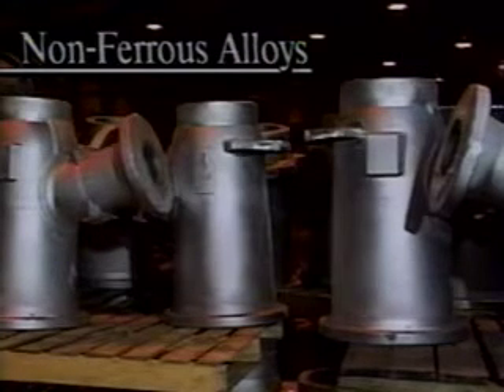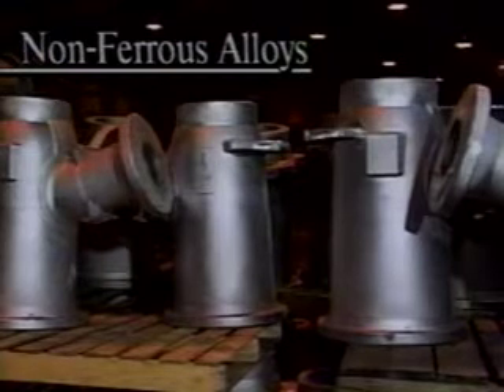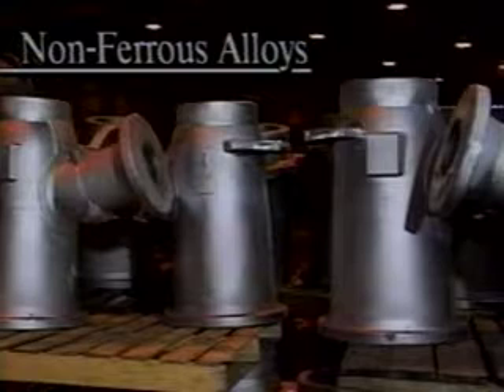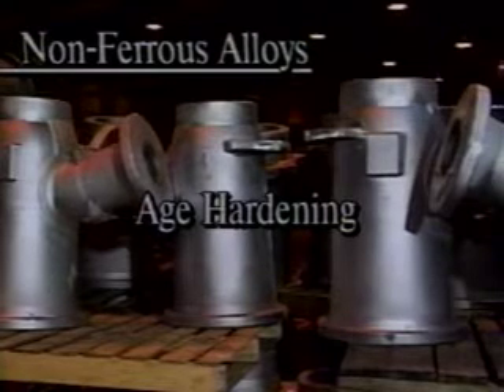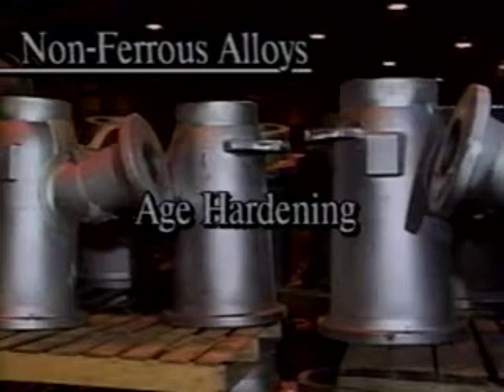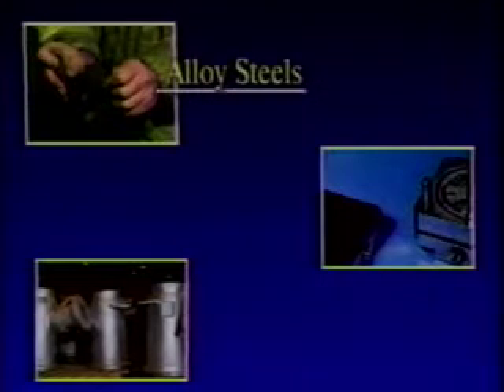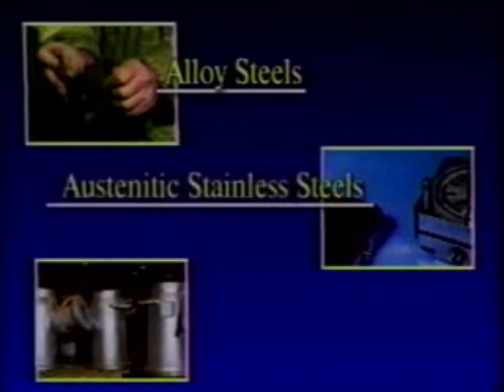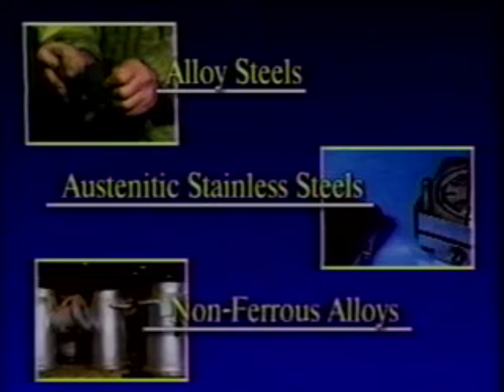In some aluminum alloys, the hardness of the quenched workpiece is increased by leaving it at room temperature for a long period of time. This is called age hardening, or simply aging. Metallurgists now understand that this, too, is precipitation hardening. In each of these three cases, quenching is simply the rapid cooling of the material. However, depending on the alloy being quenched, the quenching can lead to very different results.